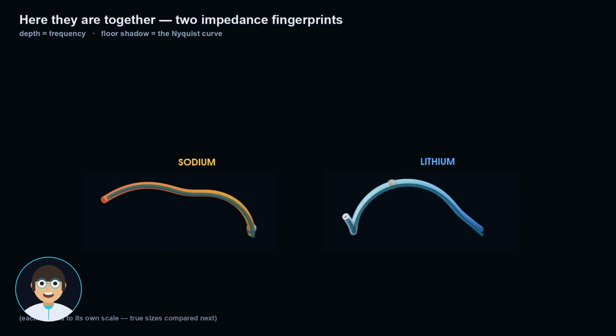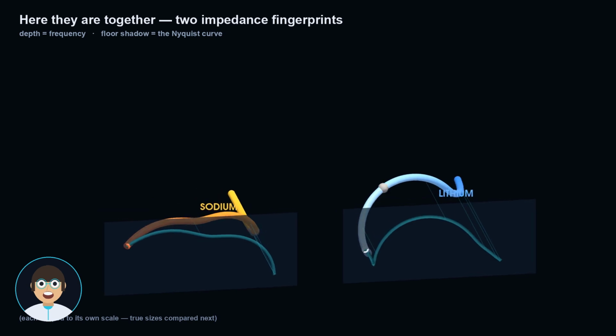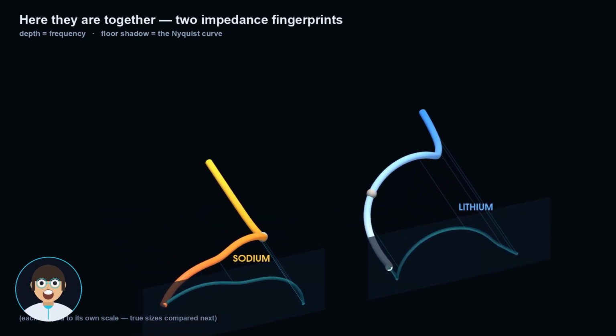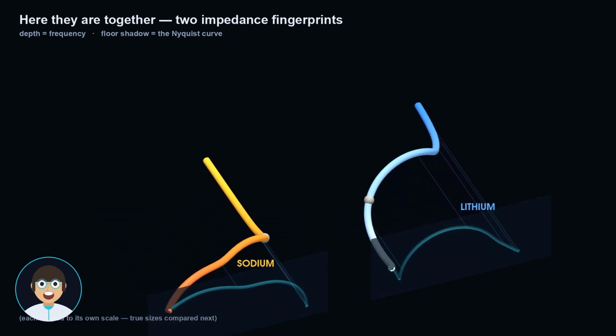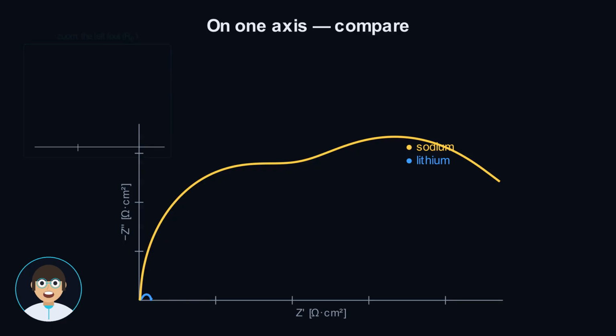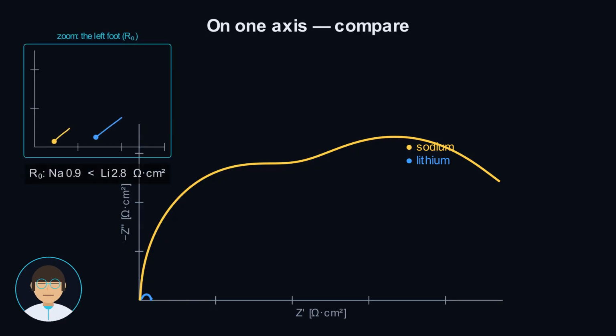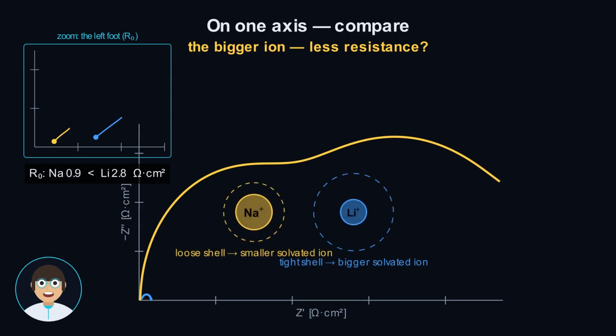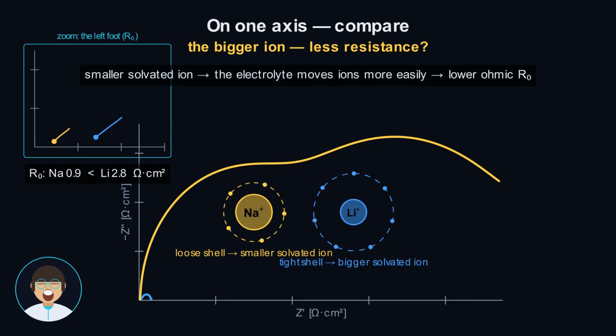Here they are together, on one axis, and the very first surprise is right at the start. Look at where each curve touches down on the left, the ohmic resistance. Sodium is actually lower than lithium, about 9/10 of an ohm centimeter squared against nearly 3. The bigger ion, less resistance? Yes, because sodium holds its solvent shell more loosely, so the electrolyte around it actually conducts a little better.